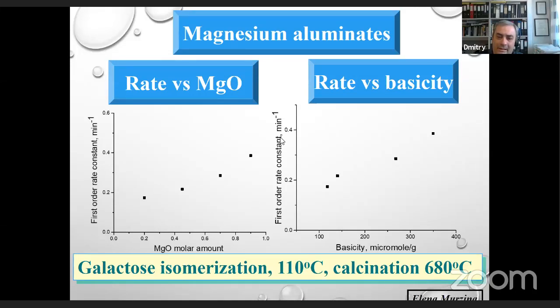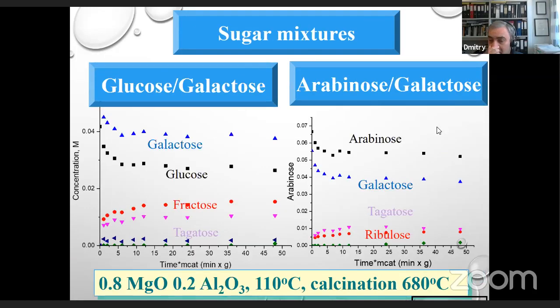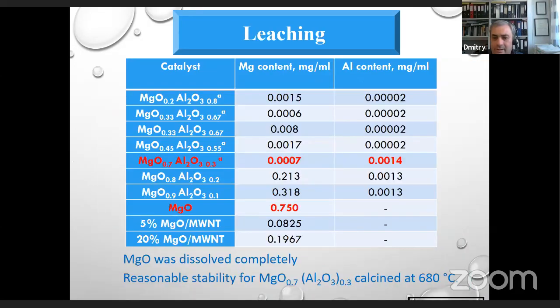Dependence of the rates versus the mole amount of magnesia, or maybe more scientifically correct, the rate, or actually more precisely the rate constant, as a function of basicity, showed almost linear dependence for magnesium aluminates. It's also possible to do this isomerization for sugar mixtures. We were using glucose, galactose, arabinose, galactose mixtures. And in principle, the catalysts were rather effective. But once again, we certainly have thermodynamic limitations here.